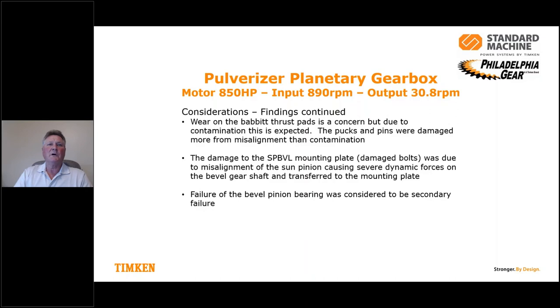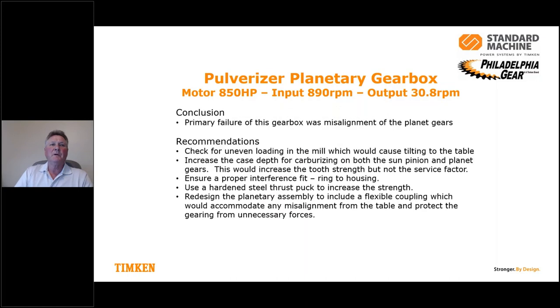Our findings continued. We saw a lot of wear on the Babbitt thrust pads. The pucks and pins were damaged from misalignment more than from contamination. The damage to the spiral bevel mounting plate basically told us there were severe dynamic forces on that bevel gear shaft that transferred to the mounting plate. The bevel pinion bearing itself was really a secondary failure. So our conclusion, in the end, pointed directly at the primary failure, which was the misalignment of the planet gears to the gearbox.